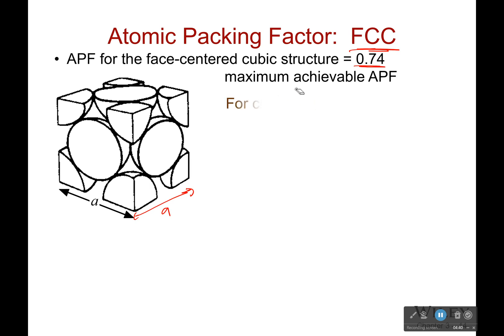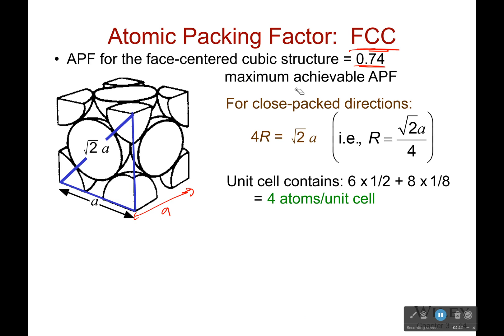So, well, how are we going to do that? Well, it's not too terrible. First, we look at our close-packed direction. That's where the atoms are touching each other directly. So you look at this line right here. These atoms are touching right there. These atoms are touching right here. This is my close-packed direction. I have no room to move without hitting another atom in that direction. I'm touching an atom along that direction. So we know what the height is. It's a. We know what the base is a.